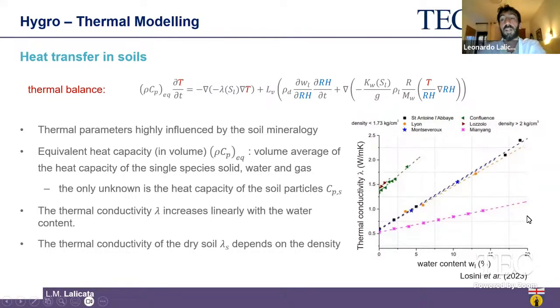These are data collected by Losini et al. You see that the thermal conductivity increases with the water content, and this again is reasonable because water is a very good conductor. So the more water we have, the higher the global thermal conductivity of our material. And in the other case, you see that the dry thermal conductivity, which is the thermal conductivity of the soil particles, increases with increasing density, because conduction works better if the soil particles are in better contact. And this is what you get when you have a high density in your samples. So this is a linear trend.